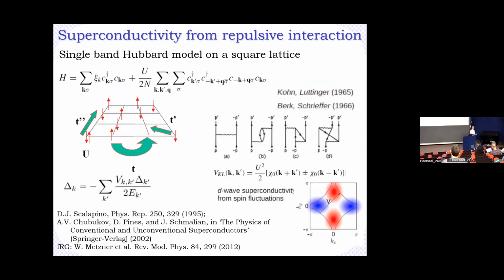And in this audience, I don't have to mention that the typical situation when you have an unconventional superconductor is that there is an overall repulsive Coulomb interaction, and this repulsive Coulomb interaction starts to interfere with Fermi surface topology. It's just a matter of, if you want, an accident that in the case of the cuprate superconductors, you have a nearly half-filled Hubbard band in the Fermi surface where you have a hotspot, and the superconducting gap due to repulsive interaction is trying to change sign, and you have experts in the audience, which is giving you a D-wave symmetry of the superconducting order parameter.